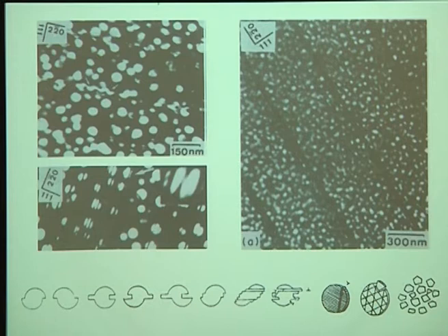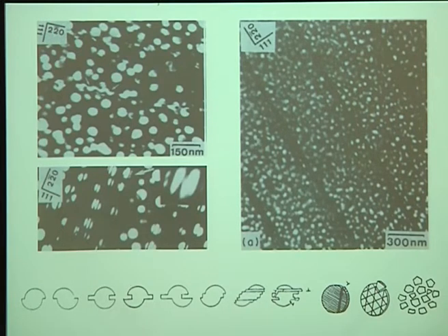Many multiple slip systems, when they start acting, what is the effect of this? We can think that initially dislocations are moving on one slip plane, then on another parallel slip plane they remove it, like this it will be happening, and then another slip system which activates will be cutting these slices into small sections. And if the number of cycles is more, the size becomes so small that they can dissolve, be smaller than the nuclear size.